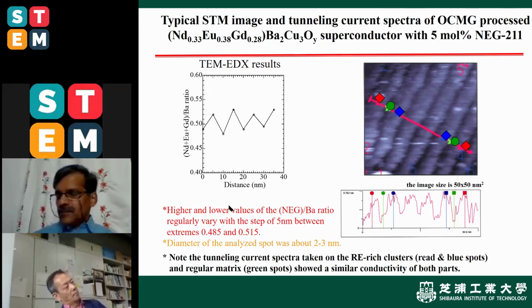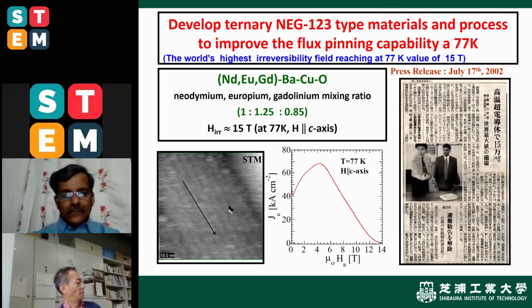You can see the nanostructures are close to around 4 nanometers, close to the coherence length. As a result, it was improved. This is also the world's highest irreversibility field so far reported, 15 Tesla. This was again in the press release and on TV channels in Japan.